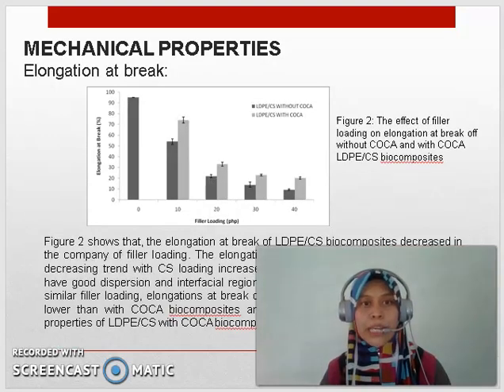Property number 2, elongation at break. Figure 2 shows that the elongation at break of LDPE/CS biocomposites decreased with increasing filler loading. The elongation at break of both biocomposites shows a decreasing trend as CS loading increased, due to the presence of COCA, which has good dispersion, and an interfacial region between filler and matrix is formed. At similar filler loading, elongation at break of LDPE/CS biocomposites with COCA is lower than without COCA, and the presence of COCA shows plasticizer properties.